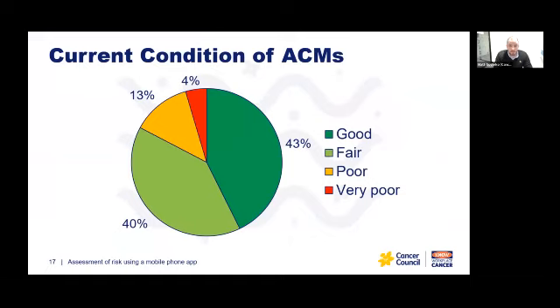Based on the priority assessment, the majority of ACMs in this sample were assessed as being in good condition or fair condition at the moment. However, this means that about 17%, or nearly between 1 in 5 and 1 in 6 houses or materials, had potential ACMs in poor or very poor condition. So it's important to note that ACMs are aging and have now been in place for a minimum of 40 years, upwards of 80+ years, which means many ACMs are potentially reaching the end of their lifespan, and their condition is likely to worsen.